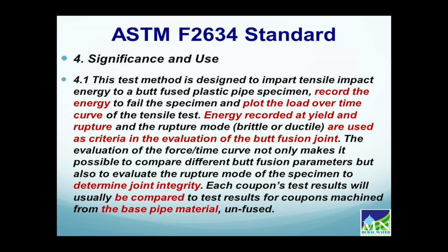This is the actual significance and use of the ASTM standard. As it says, the test method is designed to impart tensile impact energy to a butt-fused plastic pipe specimen. So it's perfectly adequate to use this test method on PVC. Key, though, is that you record the energy to fail the specimen. You plot the load over time curve of the test specimen, and the energy recorded at yield and rupture and the mode are used as criteria in the evaluation of the butt fusion joint. So this is a very good test method, ASTM test method, to determine the integrity of a butt fusion joint.